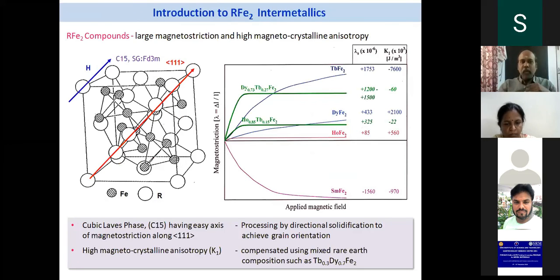This is how the typical structure looks, whether TbFe2 or DyFe2, whatever the rare earth alloy you take. This structure is a cubic C15 Laves structure with a space group of Fd3m. This material is highly anisotropic, that means the magnetic properties are different along different crystallographic directions. The easy direction of magnetization in this material is along the 111 direction.